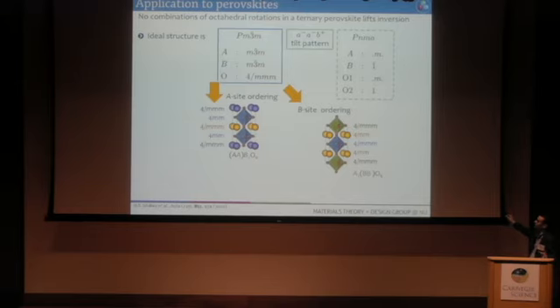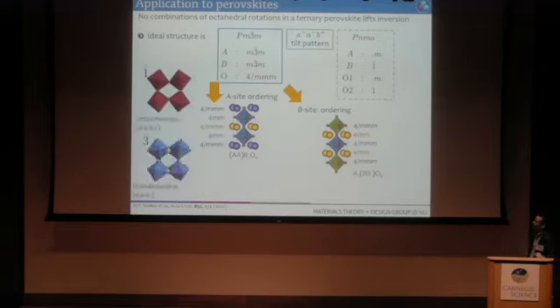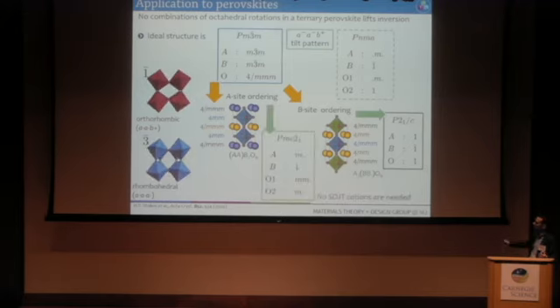This is the consequence on the Wyckoff symmetries, site symmetries in the absence of chemical order. And then I just take combinations. And you find, those are what the tilts look like. I take combinations, and I can see, okay, if I have B-site chemical order in, say, a 1-1 period superlattice, this preserves inversion symmetry on the B-site. If I take this tilt pattern, combine it with that one, I lift all inversion centers in the structure, and I have a polar compound.